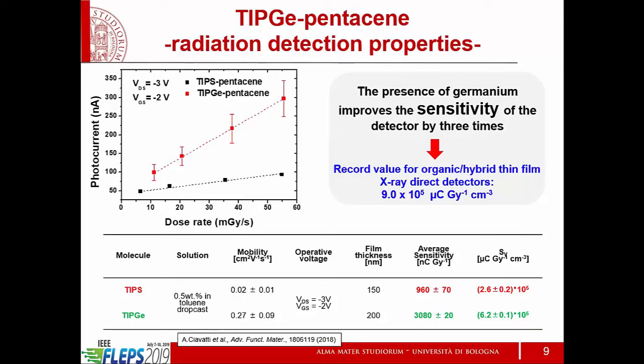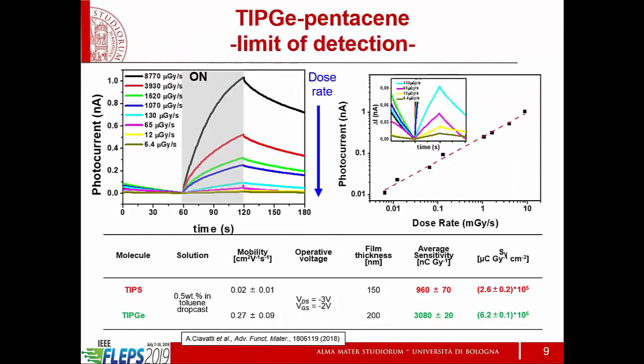Now, that is very interesting because it allows us to further increase the sensitivity of these devices. But what we think is really interesting is not just the record values, which is really good, but the idea that we think we have a way of controlling the way these films and these devices can work. That is another very interesting figure of merit, which is the limit of detection, which can be of interest, again, for certain applications. If you want to use the detector under a strong proton beam, of course, this is not an interesting issue. But if you want to measure small contamination, that is important.